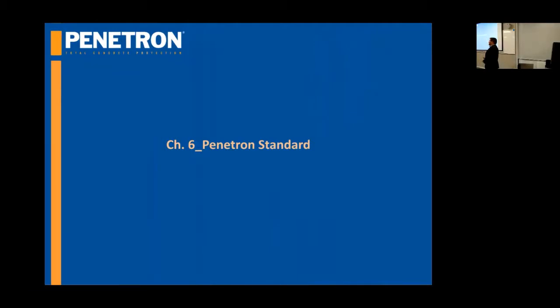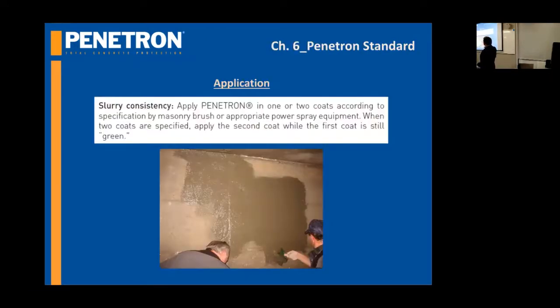Another product is Penetron Standard, and now we are going to approach the repair and the technology for infrastructure. Penetron Standard is fundamental for all the structures, while Penetron Admix is an admixture to be added on the concrete or on mortar. Penetron Standard is a slurry to be applied on concrete, and it penetrates inside. The more water there is, the more it reacts and it works. It's not a coating that you apply, and if you remove it, it will still work. The slurry seals all the cracks up to 0.4 millimeters.